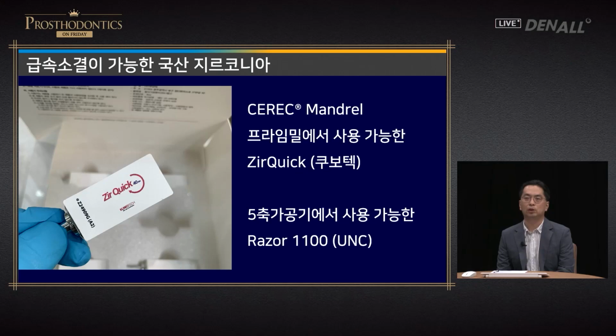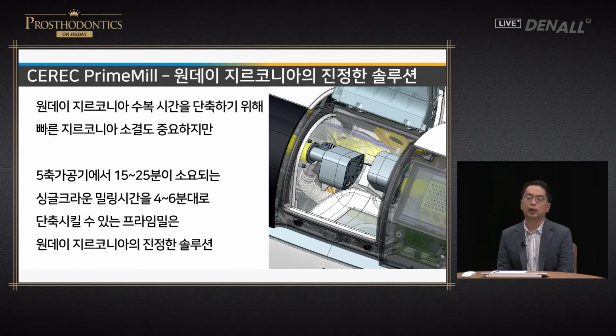Now I'm going to talk about what kind of zirconia can go through speed sintering. Using a 5-axis milling machine, you can use Razor 1100 and CEREC Mandrel, you can use a Zirquick. Milling is very important in a 5-axis milling machine. It will take 15-25 minutes, but in a PrimeMill, this would be reduced to 4 to 6 minutes.